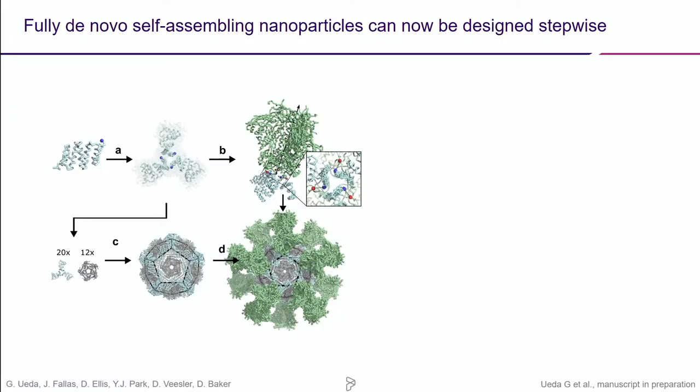One of the things that we've also turned to recently is full de novo design of these nanoparticles. The examples that I have shown so far use naturally occurring protein building blocks. But now we're making up the monomeric protein completely de novo, and then using those to form oligomers that are tailored for genetic fusion to antigens of interest. We put, for example, the N-termini here as blue spheres, in just the right geometry such that we can fuse, for instance, HIV envelope from its C-terminus to the N-terminus of the nanoparticle subunit.